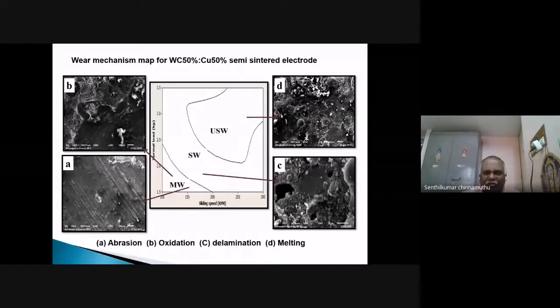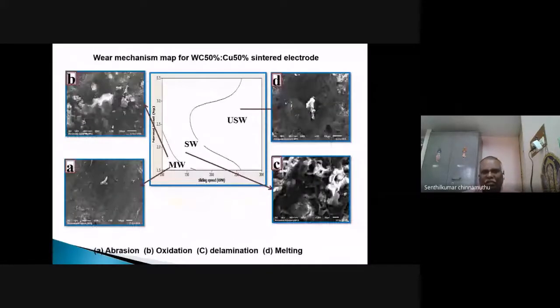Then the wear mechanism map for the 50% tungsten carbide and 50% copper sintered electrode. The mild wear region is up to 160 sliding speed and the normal load is up to 2.4. So abrasion and oxidation take place in the mild wear region, as we already saw in the semi-sintered electrode. The abrasion is nothing but the scratches. The oxidation is the removal of the oxidation layer and removal of material. So this is the mild wear region, which is the safest zone.